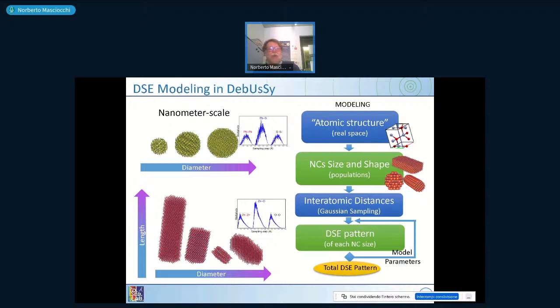So for every single particle, you can construct the histogram you've seen before. Here you have it separated for the first case, the lead sulfide sample we've seen before. And down there we have zinc oxide, which is normally crystallizing in a wurtzite type with some rod system. You have a different shape of histogram, which has a tail on the side. The tail is given by the fact that your material is not isotropic in shape but has a longer direction, so there is a certain probability to have much longer distances than the shorter ones. And so these are the input distances which are used by the DSE equation.